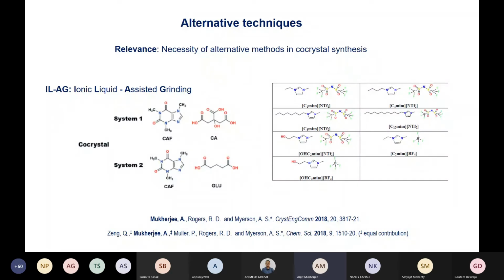In a previous study, we had shown that ionic liquid can help in crystallization. Ionic liquids have been around for many years, but their use in crystallization is limited mainly because of viscosity and other factors, such as lack of evaporation. So we thought we could use this ionic liquid assisted grinding technique here, mainly because it provides the same advantage that polymer assisted grinding provided. In addition to that, ionic liquid can be tuned both by the chain length of the cation and also by its electronic nature.